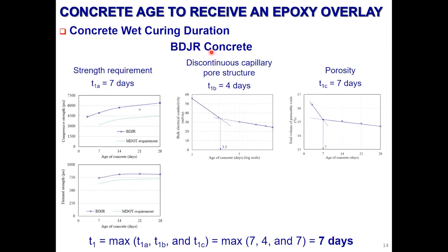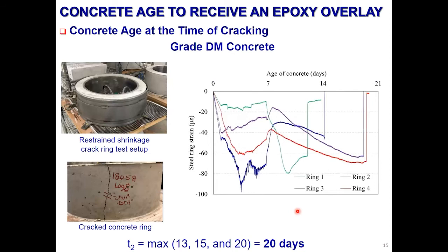For the mix with type 1 cement, actually 7-day moist curing is adequate, because we can have a discontinuous capillary pore structure a little after 3 days, and the minimum permeable voids we can see around 7 days. So with that, we can discontinue wet curing after 7 days. So it depends on the mix. As I mentioned previously, in order to apply overlays, we want to have concrete cracked, unless we use some other concrete that will never crack. That's not the case with typical concrete; it's going to crack.